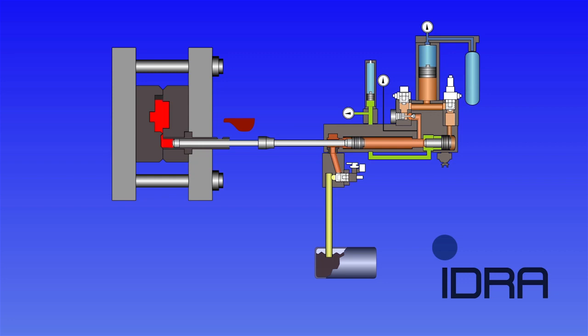At the end of the filling of the die it is also possible to brake and reduce the impact pressure experienced within the die. This helps to eliminate flash and gives the production engineer the chance to fill the die with higher speeds than traditional injection systems.